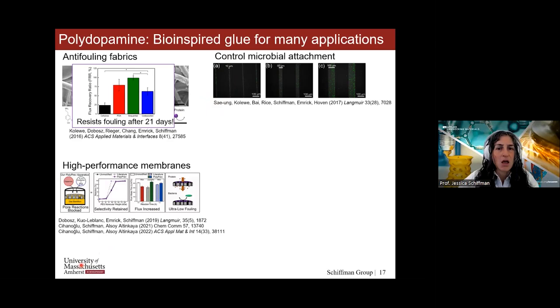We've also used the same chemistry trick on membranes in a few different applications. What I'd like to point out that my students did that was really smart in this case is that here we are treating the membrane with dopamine and polydopamine. But like I said, this reaction only happens at a pH of 8.5 in the presence of oxygen. So we actually blocked oxygen from getting into the pores of the membrane. This meant that we only coated the surface and not the pores of the membrane. And if you know about water treatment, this is super important because membranes work really well. We just want to keep them working for longer. So here we had the same selectivity, the same ultrafiltration membrane, with a higher flux performance and very low fouling.